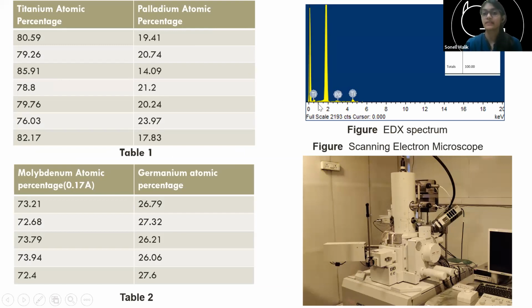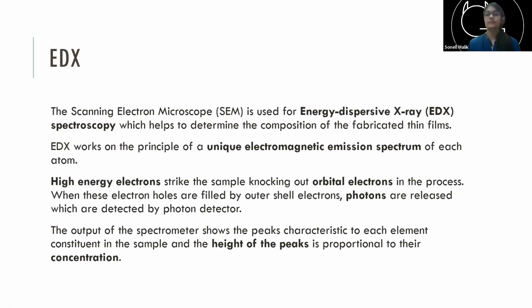So I mean, say here, I detect a particular number of electrons for titanium. It's hard to see here because these other peaks are quite big. But if I zoom in, then for palladium the peak is much smaller, which means the concentration of palladium is also much smaller. And you can see here, palladium was around 20% of the sample, titanium was around 80% of the sample. So yes, the height of the peak is basically directly proportional to their concentration in the sample that you want to examine.